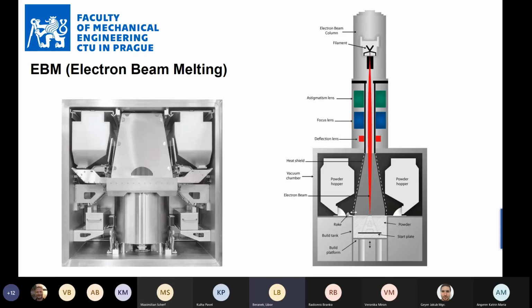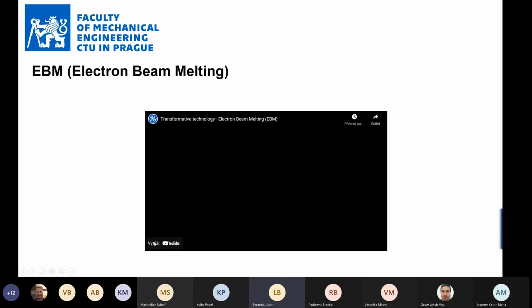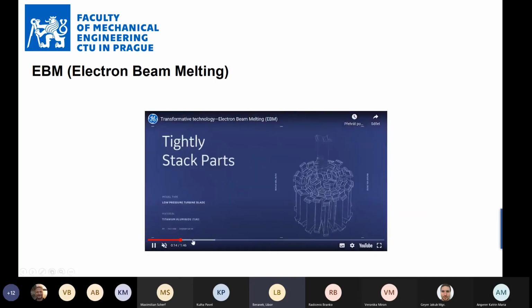It has better precision when you compare the form deformations, because the form deformations are here minimized by preheating. But again, the surface finish or the surface quality of the part is much, much worse. The surface roughness parameter Ra is usually double or sometimes even triple that of the DMLS technology. So then you have to spend more time on finishing of those parts. So this also comes into consideration. You can see for the electron beam melting, if you are interested, I will give you this presentation.